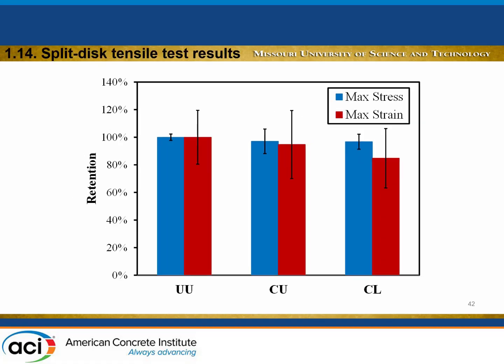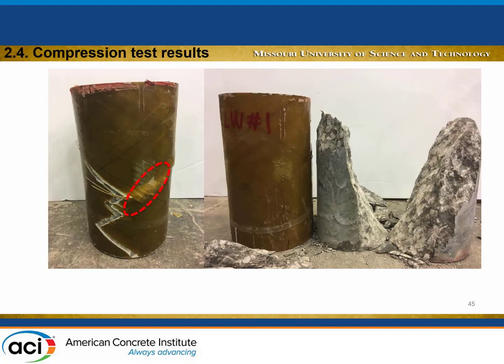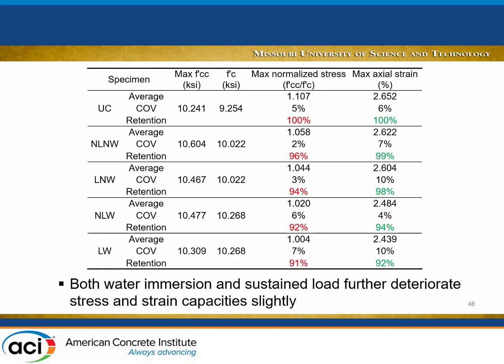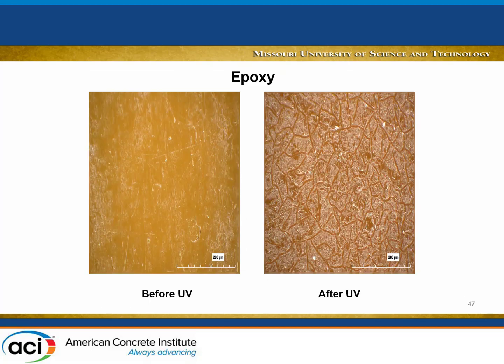This one was placed in water inside the environmental chamber. Again, the mode of failure: we found one interesting difference. With the epoxy, we start to see some delamination first, versus the polyester, where we see a complete pull out of the fibers from the resin. Looking at the specimens placed in water, we didn't really see much difference. The epoxy is much better than the polyester here. For example, if you have the unconditioned, the retention is 100% in terms of axial strain. But when you expose them to load and water, we lose about 8% in axial strain and about 9% in hoop strain. So you don't really lose much after probably 3 months of exposure in water.